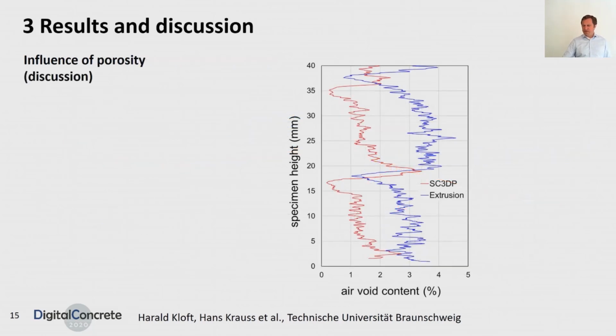Now I'd like to discuss two main possible reasons for the results we observed. Firstly, I'd like to present you the results on the porosity distribution or air void content distribution over specimen height. We analyzed this by computer tomography. For details, please take a look into our paper.